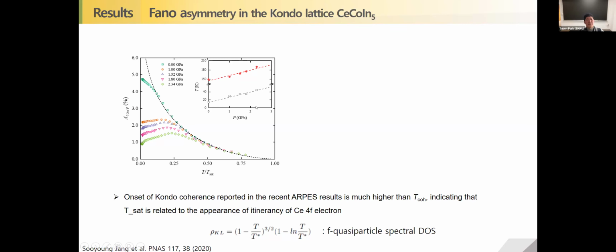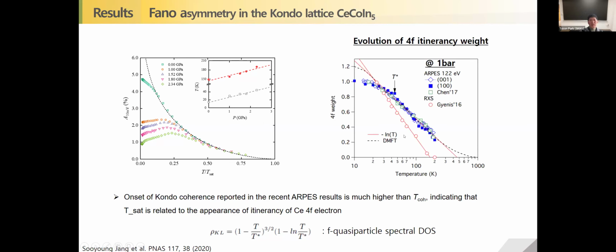Here is the saturation temperature versus pressure, in red, where this type of scaling behavior appears. The temperature range is much higher than 100 Kelvin, which is well above the coherence temperature. The figure on the right is the ARPES result by Sooyoung Jang et al. As you can see, this 4f weight in the spectrum occurs not below the coherence temperature, but well above it. So we think that this saturation temperature, where the Fano asymmetric behavior appears, is associated with the itinerancy of the cerium 4f electron.